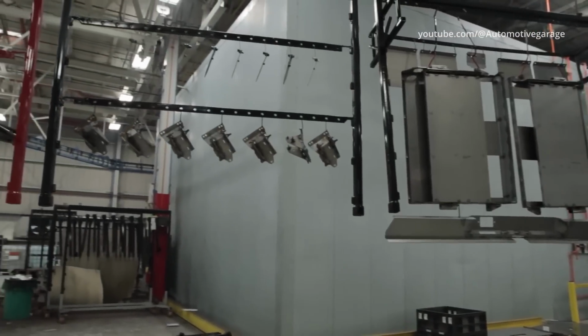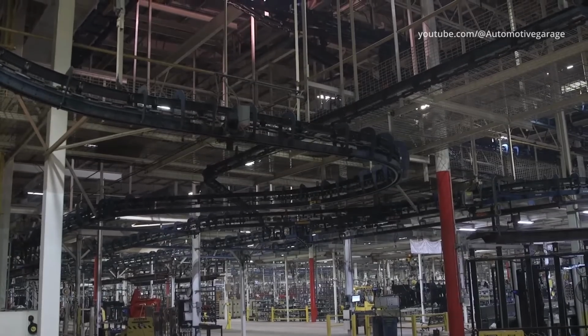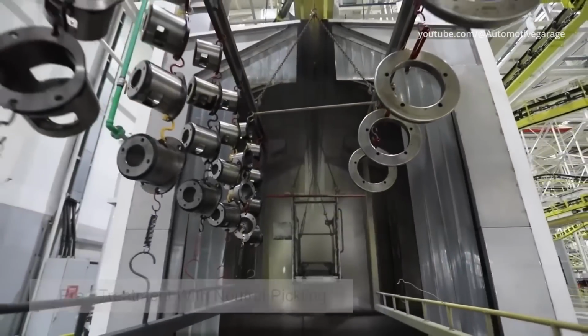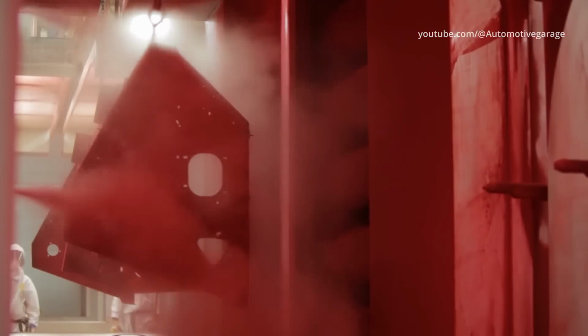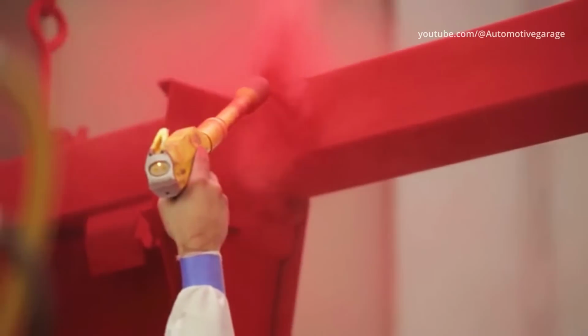Primary steel components, including cab structures, are individually corrosion treated with an alkaline cleaner and then a zirconium metal conditioner. Steel elements are then primed and undercoated before thermoset acrylic painting is carried out on a line which stretches to 4 kilometers. A total of 95 liters of paint is used per combine, followed by oven baking to 169°.